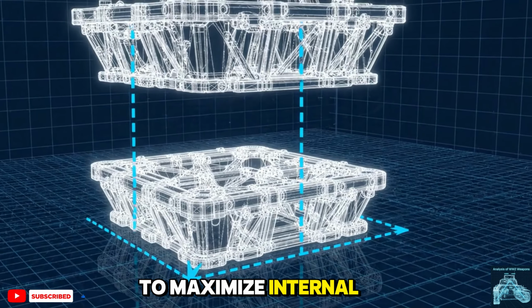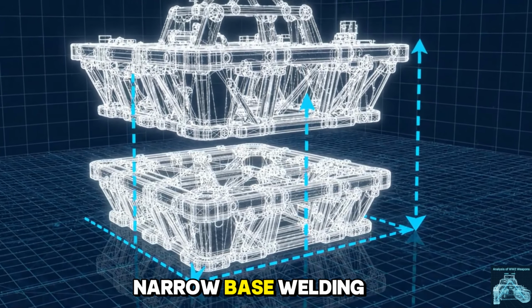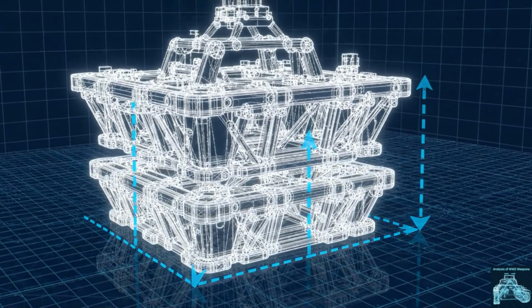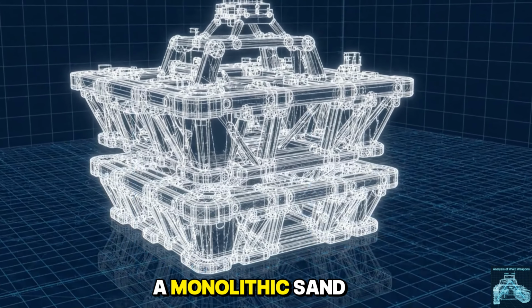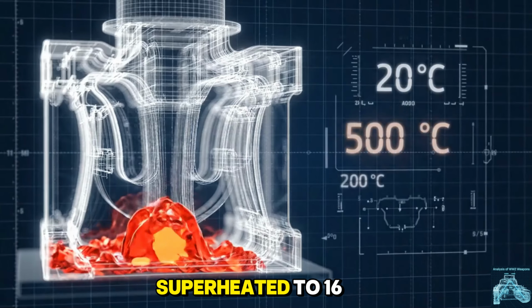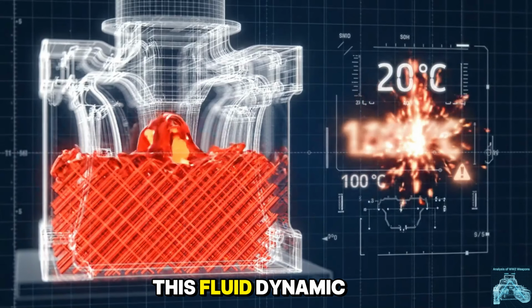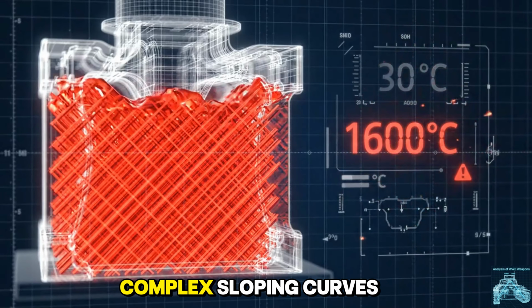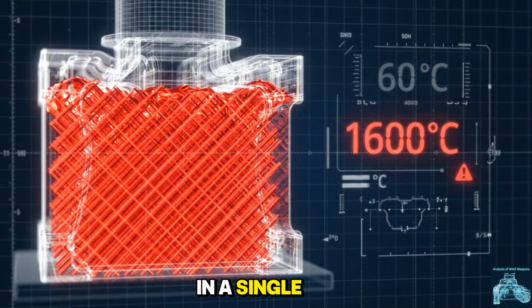1,420mm. To maximize internal volume and defensive curvature on such a narrow base, welding flat plates was rejected. Instead, engineers utilized a monolithic sand casting process. Liquid steel, superheated to 1600 degrees Celsius, was poured directly into the void. This fluid dynamic naturally formed incredibly thick, complex, sloping curves in a single, seamless piece.